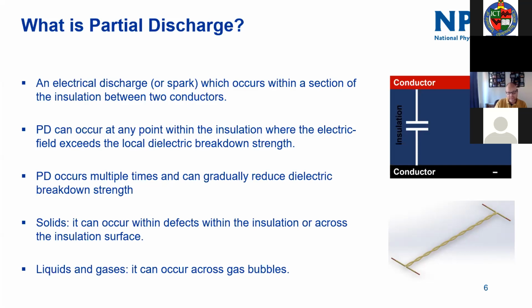The PD can occur at any point within the insulation, and it's where the local electric field strength exceeds the local dielectric breakdown strength. It can occur multiple times, and it will gradually reduce the dielectric strength. And perhaps I'll show you some examples, one of which is PCB based.